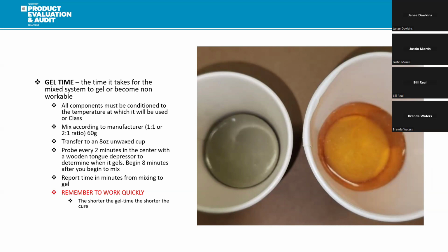So you want to keep that in mind because you have so many different classes of the material. You want to mix according to the manufacturer's mixing instructions. It's either going to be a 1-to-1 ratio or a 2-to-1 ratio, but either way, it's going to be 60 grams of the material. You want to transfer it to an 8-ounce unwaxed cup. It's just a little Dixie cup like you would have in your bathroom. Once you transfer it, you want to probe it every 2 minutes in the center. You just want to poke it a little with a wooden tongue depressor to make sure it gels. This begins about 8 minutes after you begin to mix.